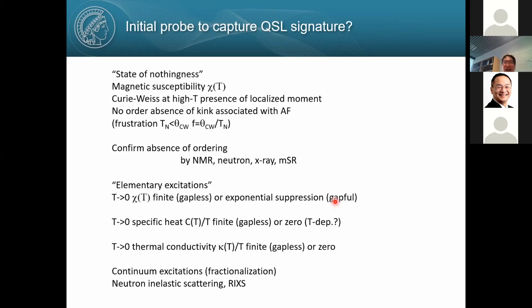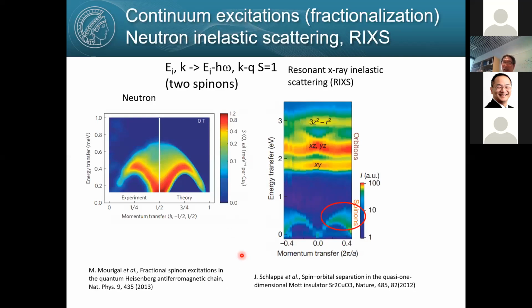Meanwhile, if you measure specific heat, like a metal, zero-energy excitations give rise to T-linear specific heat, so you should have finite T-linear specific heat in the case of a gapless quantum spin liquid. Nowadays everybody is interested in measuring thermal conductivity, which is a product of heat capacity times mean free path. So it measures spinons, which are itinerant, and in that sense this thermal probe is quite important. Finally, you measure neutron scattering and see whether the spin excitation is fractionalized into spinons or not, and whether you see a continuum excitation like this. That is quite an important check.